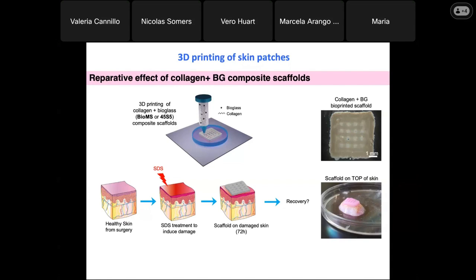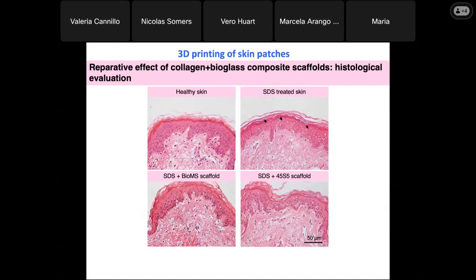heal the skin. And so you can see the histology of the skin. In the upper left, you see healthy skin, where you see the dermis at the bottom and the epidermis in the upper part. On the right, you have the SDS-treated skin, where you can see the damage. You can see the pycnotic nuclei of keratinocytes, so this means damage. And then we put the patch with the scaffold with BGMS10 and the 45S5. In both cases, we saw skin healing, which was better for BGMS10. So this is a preliminary result, but still very important because it was done with human skin. So it's not a real in vivo test, but it is done with real human skin.